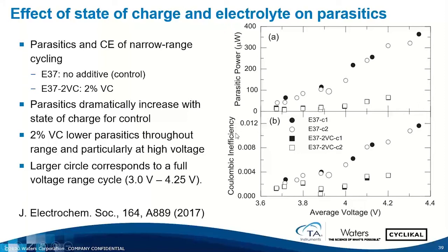So the Coulombic inefficiency, which is simply 1 minus the Coulombic efficiency. Now 2% VC is quite a standard additive to most battery electrolytes. And here's a nice demonstration of what vinylene carbonate actually provides: an enormous change in the parasitic thermal power.